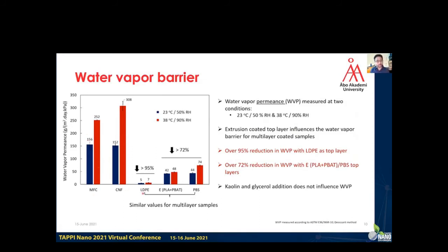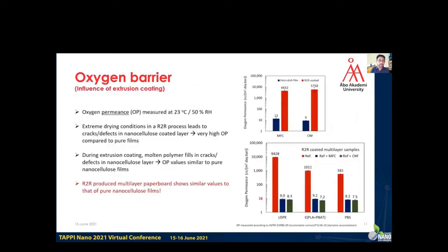But if you look at the water vapor permeance for extrusion coated samples, LDPE, Ecovio, and PBS, we see a very large reduction, like 95% reduction for LDPE and 72% reduction for Ecovio and PBS top layers. And we get similar values for multi-layer samples because it's the top layer that controls the water vapor permeance. And kaolin and glycerol addition did not show any difference in the water vapor permeance.